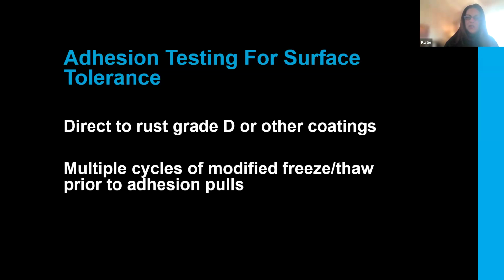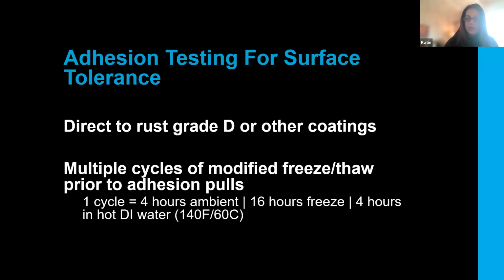So how do we mimic these changes and stresses that we might see with weathering, service changes, changing exposures? You should be looking for additional stresses or testing that mimics these. I like to see multiple cycles, modified freeze thaw testing, for example, prior to pulls. I like to see 10 plus cycles to really evaluate what these types of stresses will do. And then you'll be able to see how that coating is going to mimic the scenarios of real life, including ambient conditions, cold weather stresses, cycling temperatures, or even wet, humid, or immersive type situations. This is where we want to see how far we can take the coatings and understand how they're going to perform. So let's take a look at some real numbers again.